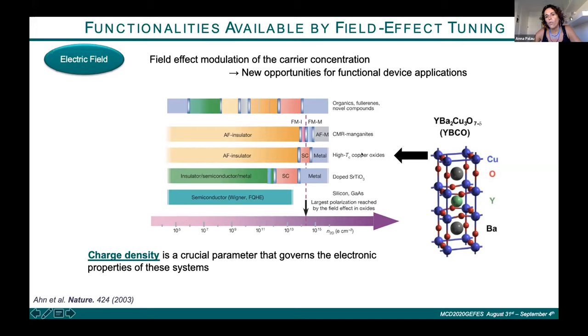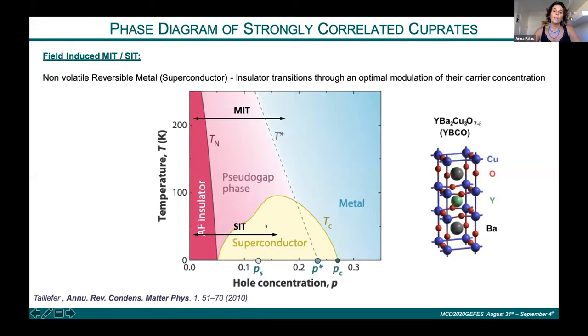And in the case of cuprates, YBCO is the one that we have studied, we can change the system from an insulating phase, which is antiferromagnetic, to a phase which is superconducting, depending on the temperature, or metallic. And this can be achieved by modulating the charge carrier density in the material. This graph here shows the temperature versus hole concentration of this material, YBCO. And what we observe is, as I said, this insulating phase at low concentration of doping carriers. And then when we dope the system, we can go to a metallic phase.